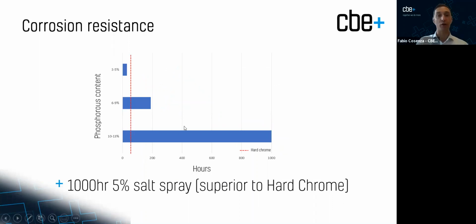On corrosion resistance also, a test that is loved by the automotive industry in particular is the salt spray. A metal testing division has a salt spray test machine internally. Again, by adding phosphorus, we can push the fail mode of electroless plating to basically in excess of 1,000 hours, which makes it pointless to carry on any further. And by comparison, you can see the red dotted line is the failure mode of hard chrome. So in terms of corrosion resistance, ENP is far superior as a performance.